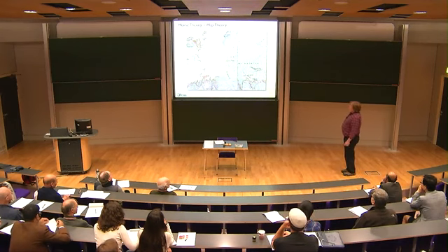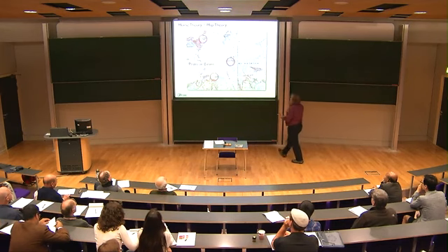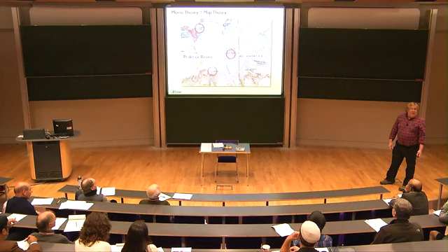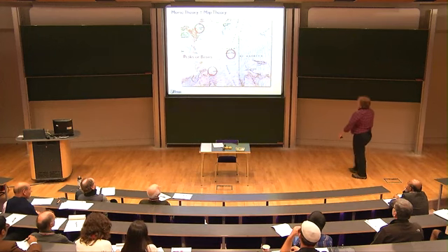All right? So that means that you have a place where the contour lines go around you, because you're at some height and all the other contour lines near you are lower than you. And so these contours, these critical points of the map, these are precisely where the +1 defects are. You see the disclination? You see how the director goes around those +1 disclinations? Of course, if it's a smectic, I don't get to put a sign on these numbers, so it could be that it's a basin. It could be the bottom of a lake or the top of a mountain. You can't tell from the contour map without the numbers.